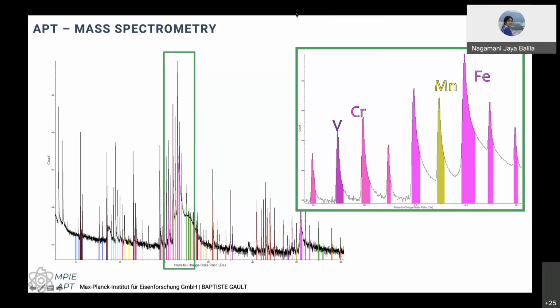So what about when we reconstruct glass samples with the reconstruction algorithms, things like nano glasses and structures like this? That's not necessarily an issue. The problem that we face is that the sequence in which ions come off is not as well determined as it would be in a crystal. So there is a loss in resolution that we can't really measure, because the way we measure resolution is by looking at atomic planes, which glasses don't have.